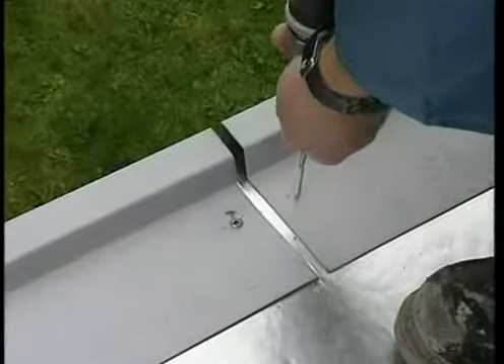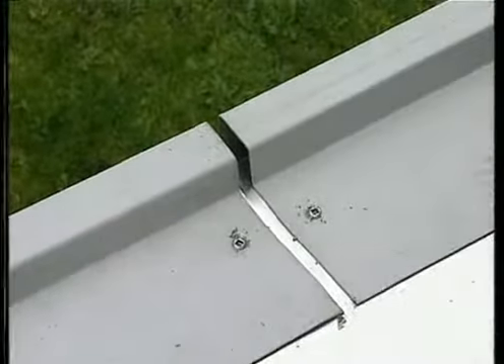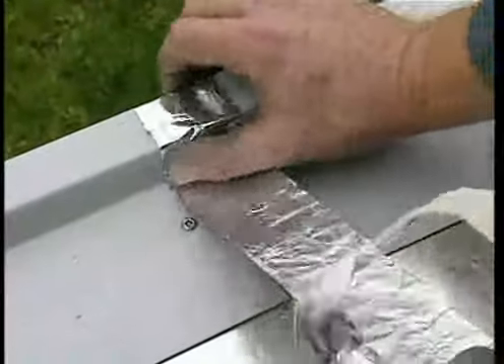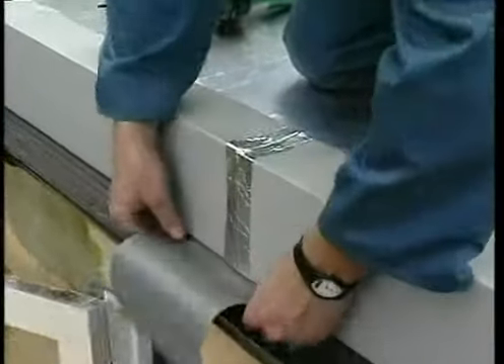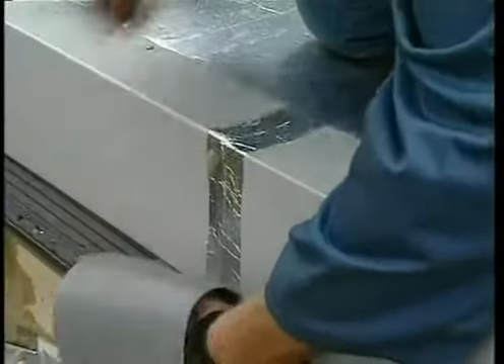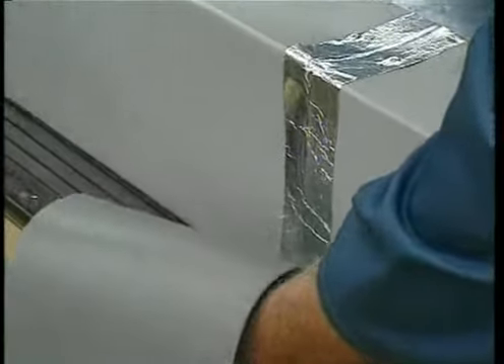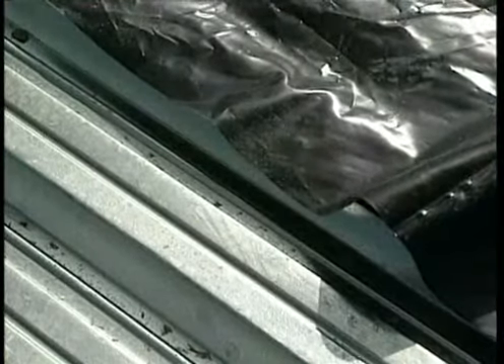An expansion gap of 5 mm must be left between adjoining sheets of metal. The gap is covered with Alkor band tape to create a 50 mm unwelded area, and the joint is waterproofed by a 200 mm wide junction strip of unreinforced Alkorplan, which is welded into position using hot air prior to the laying of the main roofing sheet.